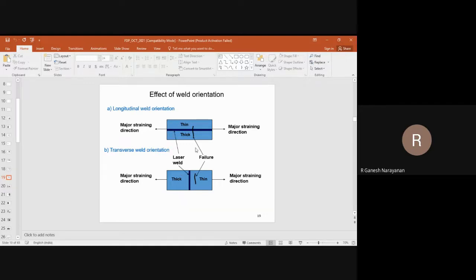And you can see this is a laser weld. When you deform this material, you will see that in the longitudinal weld, failure occurs perpendicular to the weld, because you have thinner material on one side and thicker material on the other side of the weld. But the transverse weld is very critical, because you have thin and thick on both sides. Failure can happen in the thinner sheet or in the weld zone. Thicker generally not, because it has better load bearing ability compared to the thinner one. Whichever is weaker, the thinner or the weld region, will fail. I have shown here a failure in the thinner one, but you can have failure in the weld zone also. But in longitudinal, it is always perpendicular.